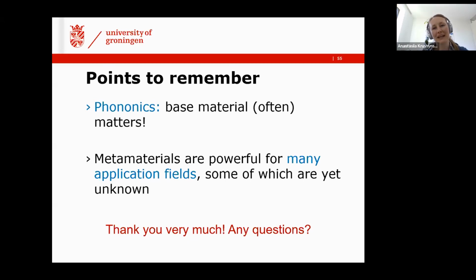But for me, these mechanical models that I used, like the generalized Maxwell model, are already a kind of effective property, because we try to put in one model, in a couple of parameters, all that complex material behavior that is dependent on the temperature, strain rate, on everything, and we try to reflect it just by a couple of coefficients. So to me, these models represent a kind of effective behavior, but I have not seen anything in terms of truly homogenization of these materials. So I think this would be an interesting research direction.